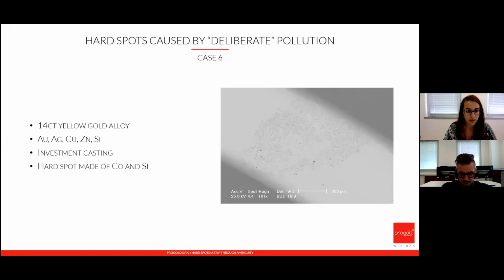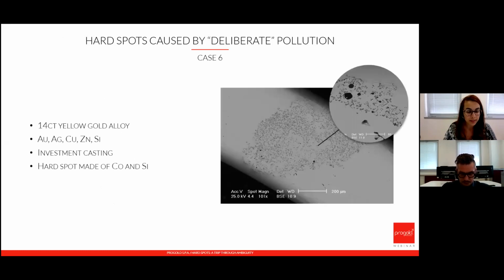In this case, we have a reaction between cobalt and silicon, and what happened here is that the person who was making these pieces was trying to harden them, but they were not reaching the desired hardness, so they thought, okay, I have cobalt at home, let's add cobalt because I know I can reach a higher hardness. But they didn't know what was inside the alloy, or what reactions could happen by adding this. They just knew cobalt could harden, and in fact, we ended up having this reaction that you see in the picture, which was very visible to the naked eye.